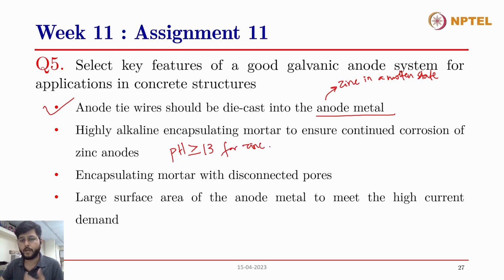So for zinc to act as an anode throughout the duration for the system to act, we have to provide a conducive environment for the zinc to get corroded, and that environment requires a highly alkaline pH of around 13. Therefore the encapsulating mortar around this zinc anodic metal has to be an active cementitious mortar, meaning that the hydration reactions are going on and the hydration products are getting formed continuously. Then the pH of the cementitious mortar will remain high, and if the pH is high, that will allow for the zinc corrosion and for the effective performance of the zinc anodic system. So yes, this is again a true statement.